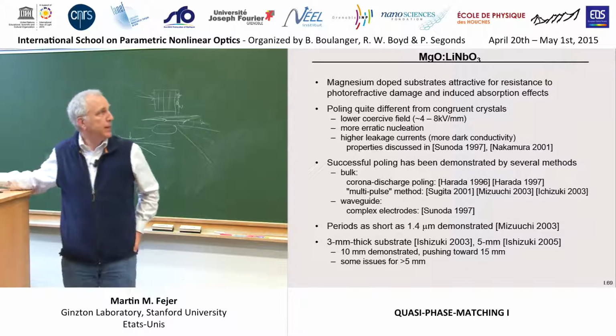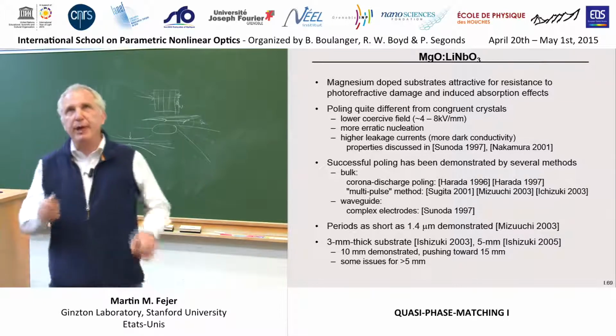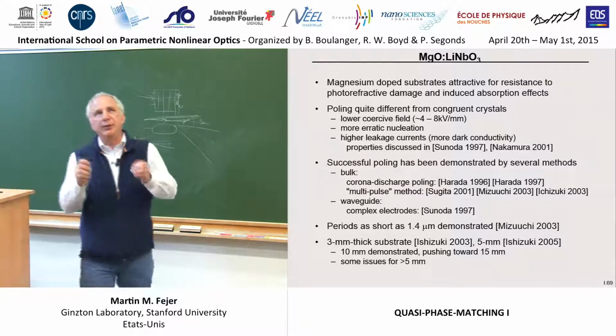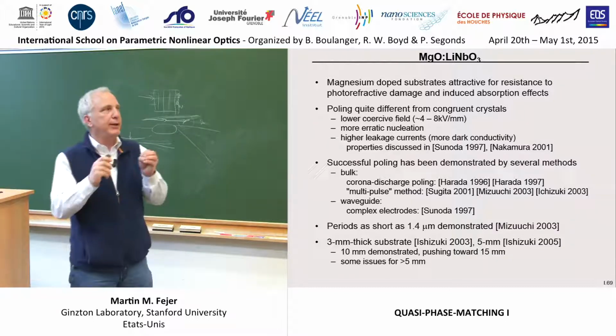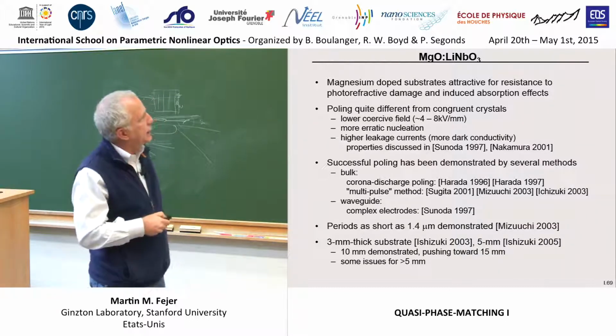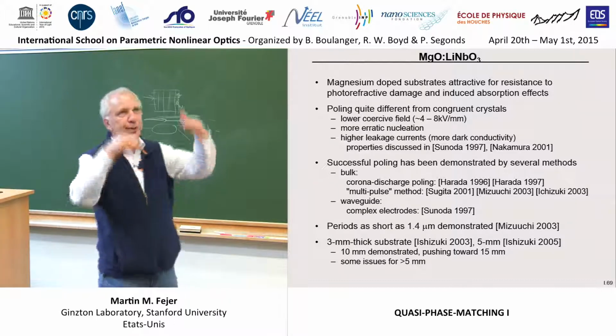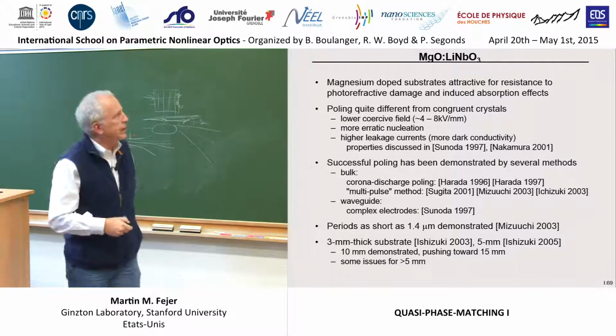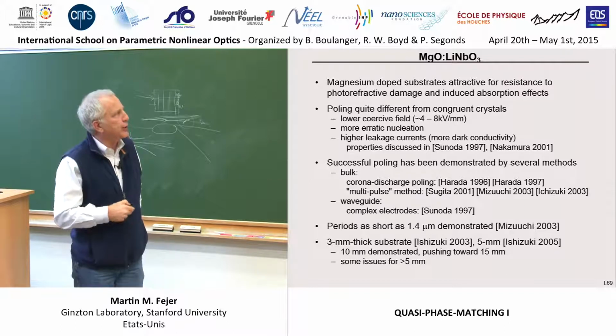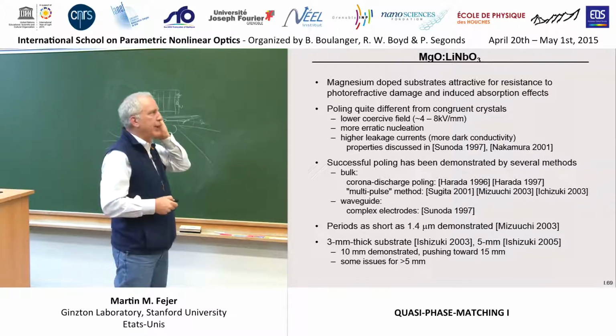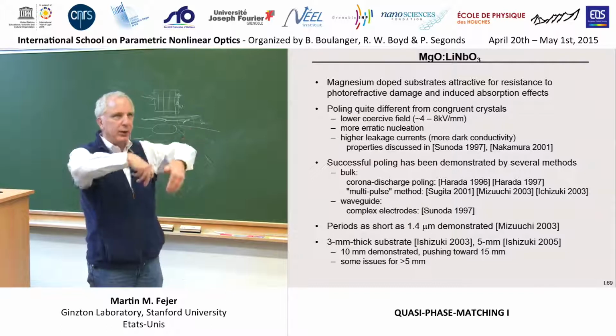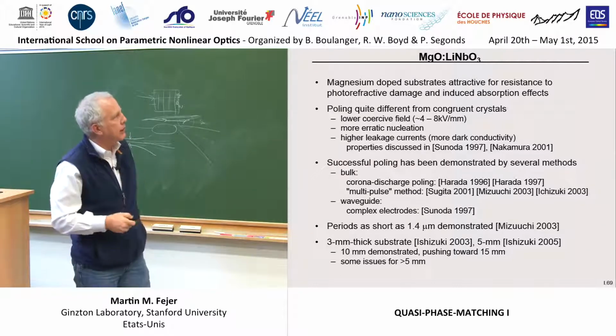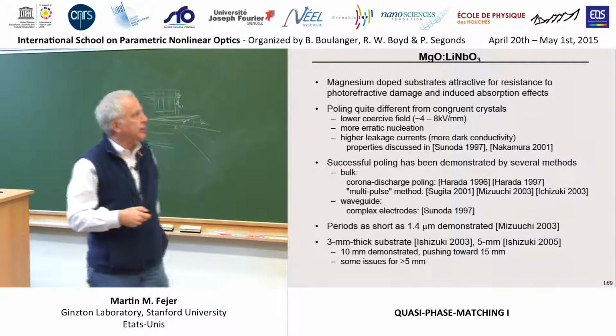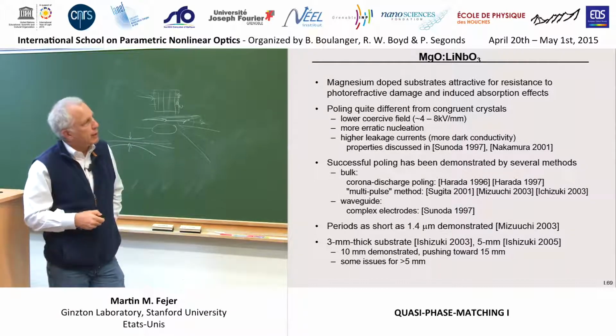Magnesium oxide doped lithium niobate, which is a popular material, has less photorefractive and photochromic sensitivity than the conventional lithium niobate. It also has a lower coercive field, which makes it easier to pole thicker samples, but it's also a bit more difficult a material to deal with. The nucleation of domains is more erratic. It is a leakier electrical material, not as good dark conductivity. Some references here talk about some of those issues. And different poling techniques are required for that material.